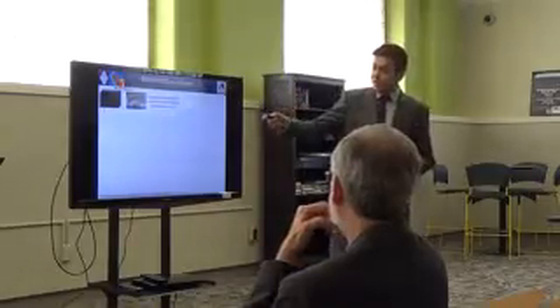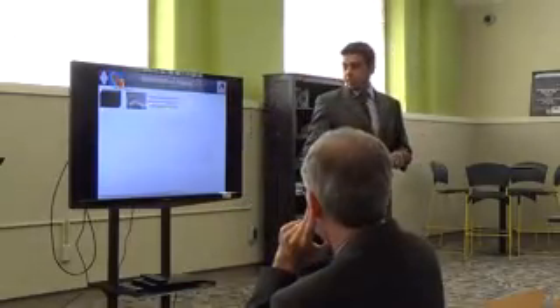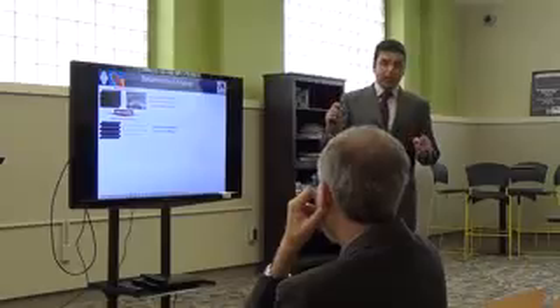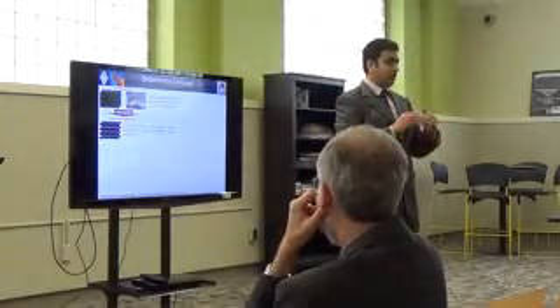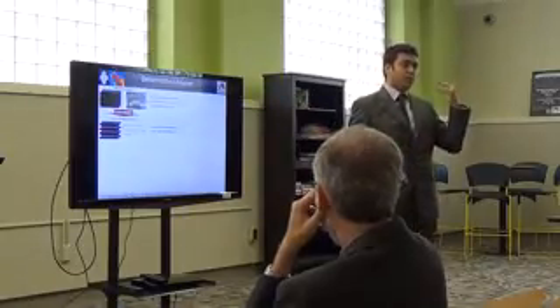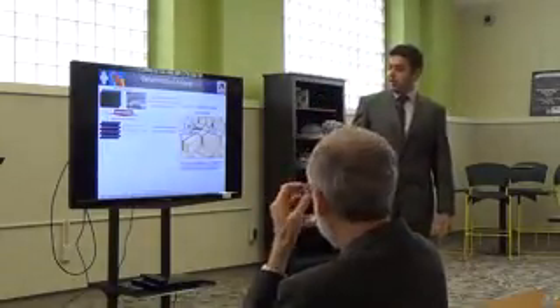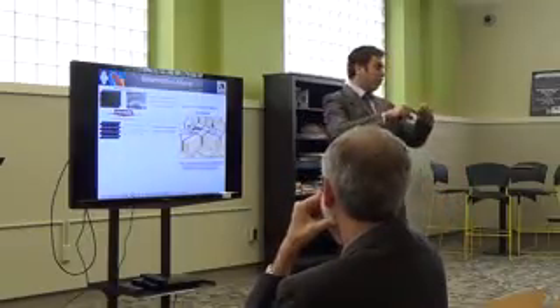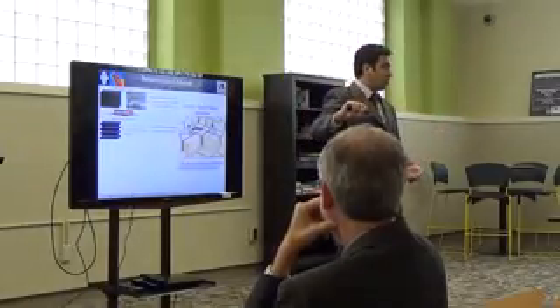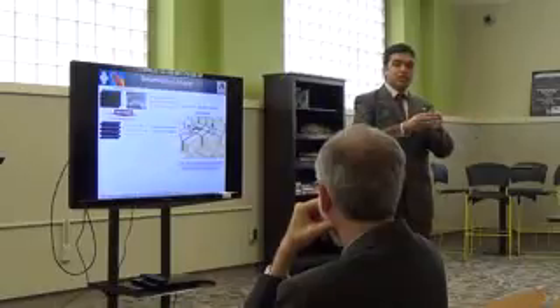More recently, all the results I was showing were on materials after the HF treatment. So we try to delaminate all the layers from each other, by intercalating something between the layers and then separating the layers more from each other. This approach was actually done by ancient Egyptians thousands of years ago. I was trying to find a picture and was not able, but I found a picture from Herod's Temple, Mount Jerusalem. They make a hole in the stone, put a wooden rod in, and then put some water on the wood. And then the wood starts to expand and separate the stones from each other.